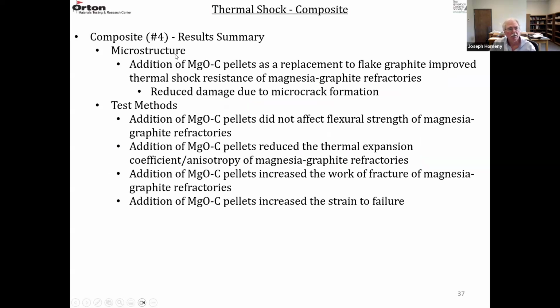So in this material, as far as the microstructure is concerned, the addition of these MgO carbon pellets as a replacement to flake graphite improved the thermal shock resistance of the magnesia graphite refractories. It reduced the damage due to microcrack formation in the coarser MgO aggregates, and the damage that was allowed to take place was primarily in the matrix of the graphite and MgO interfaces, where the MgO particles are much finer. So as far as the test methods are concerned, the addition of MgO carbon pellets didn't really affect the strength of the MgO graphite materials.